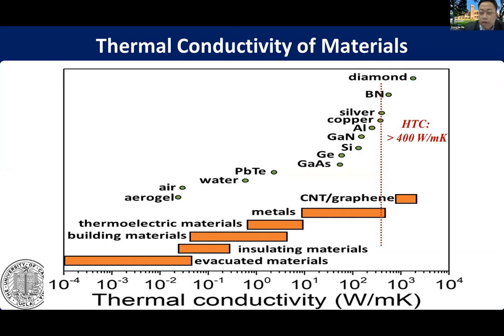So for thermal conductivity values beyond 400 watt per meter Kelvin, that's the region we are searching for new high thermal conductivity materials. Currently, we have only limited options. Diamond and cubic boron nitride have high thermal conductivities, as discussed by the previous speakers. The challenge lies in the slow growth rate, high expense, and also mechanical and other compatibility issues for semiconductor integration.